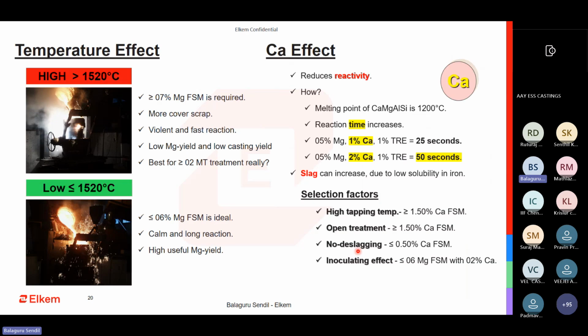The last is the temperature and the calcium. So the temperature, as we discussed, must be low. It must be as close to your pouring temperature, but unfortunately, because of how far the ladle is from the pouring, do we have to have a tundish which needs to be removed? Is the temperature loss high? Then we need to have high tapping temperature. If the tapping temperature is high, then the possibility of you using low magnesium FSM is not going to happen because the burning effect is high. So you need to go for a higher magnesium.